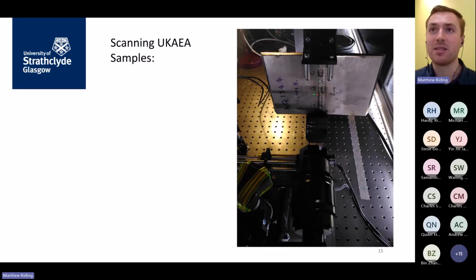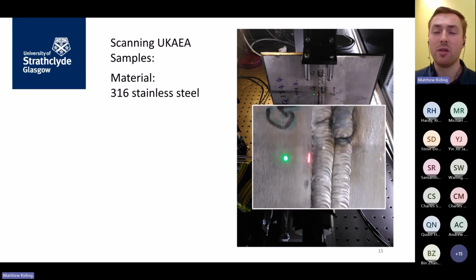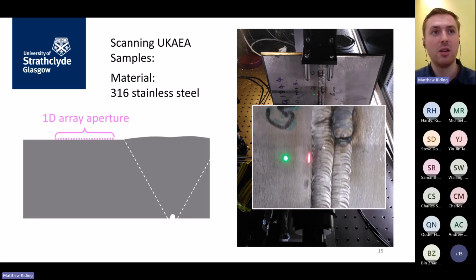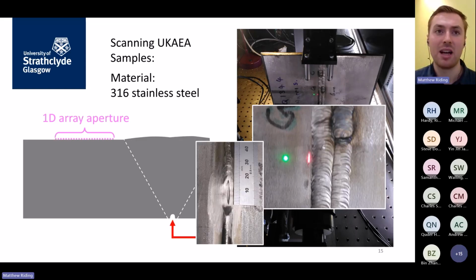So here's the plate mounted in our laboratory with the lasers illuminated on the surface. It's a stainless steel plate, austenitic. We formed a phased array to the left side of the uneven cap. We're working on going straight onto the cap, because that's something that the lasers can do potentially better than the transducers. But for now, just to make a nice comparison against the transducers, we're doing a phased array to the side of the cap. So looking at a cross section, we build an aperture up to one side of the cap, and then we're targeting the root defect, which is down there out of aperture at 12 millimeters depth, and with the following small dimensions.